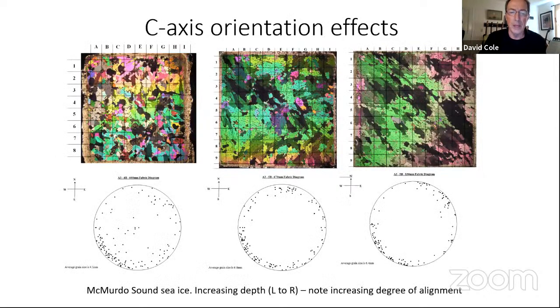A couple quick notes on the orientation effects in the model. As I mentioned, if we go down in the sheet that's growing with an under ice current, after a C-axis horizontal microstructure is established, it refines into C-axis is still horizontal, but as you can see, the orientations of individual grains are starting to coalesce around a specific direction. It's sort of a top right to lower left diagonal here where you see down at depth. So that's at about 0.8 meters.